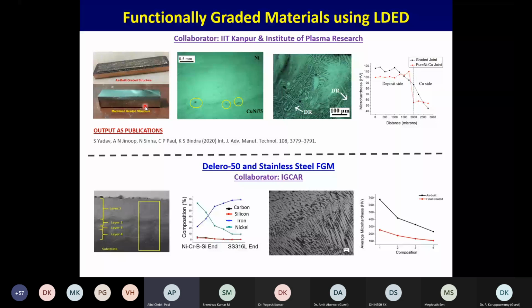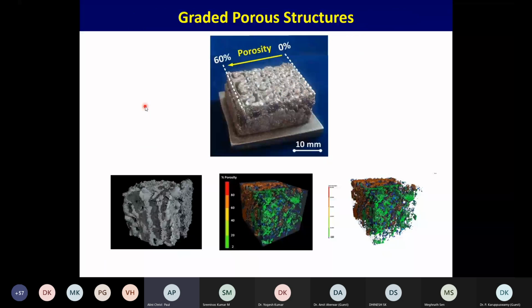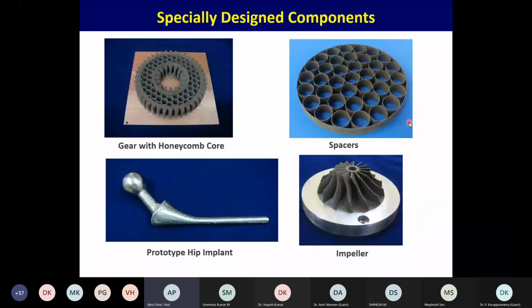I was talking to you guys and briefed you about porosity and porous structures and different aspects of it. Can you think of making a porous structure which is 0% porous here and 60% porous here? This is possible because in laser additive manufacturing we are using a pattern pencil and writing 3D shapes. Many times we have been taught that porosity is very bad in a material. It is not true. The reality is that uncontrolled porosity is bad. If porosity is under control and you know how to use it, it can be a beautiful thing to apply. Graded porous structures, porosity at defined locations, porosity at the desired size are possible, and can be done.